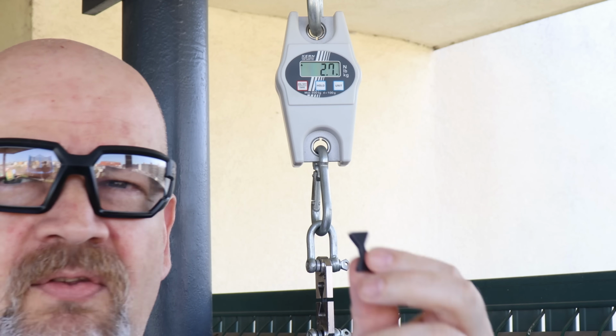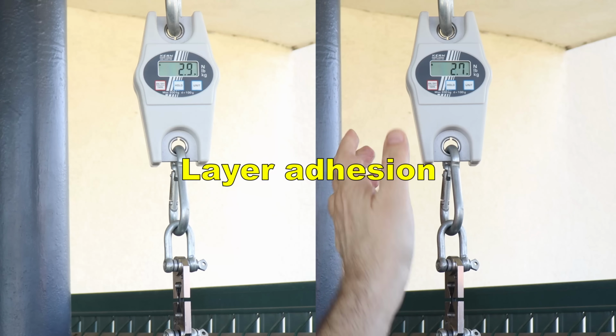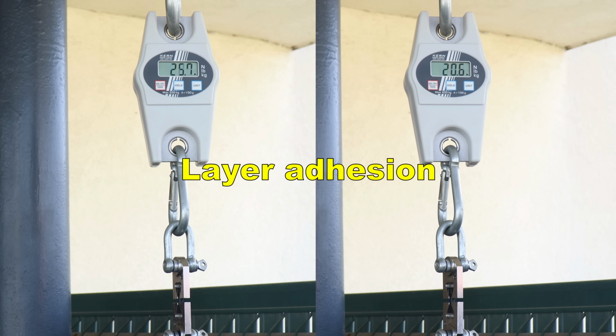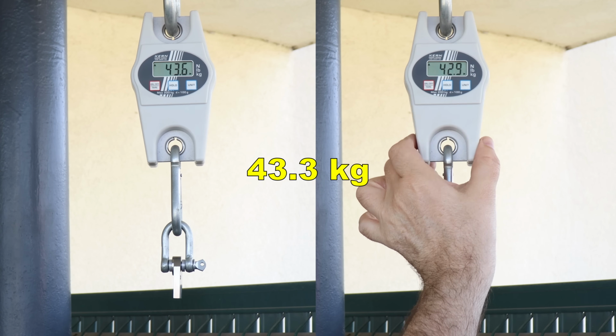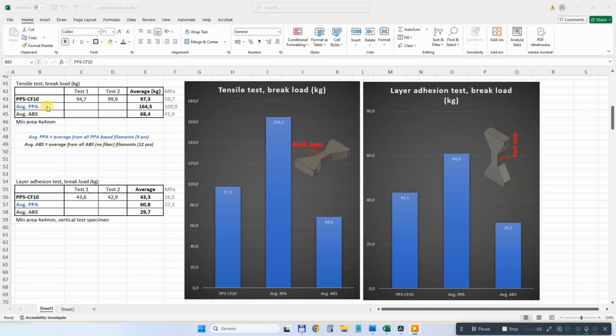I tested stronger materials. Layer adhesion test with vertically printed test objects. For better comparison, I will include the data for average PPA and average ABS materials. And we can see the PPS is somewhere between, but closer to the ABS. With the layer adhesion test, this is somewhere between, but actually this is very good layer adhesion.